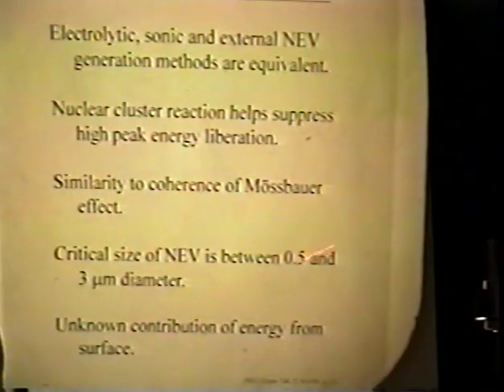At the critical size of the cluster for the kinds of energy densities we make must lie between about 0.5 micrometer and 3 micrometers in size. And we're getting a surface energy contribution from where we do not know. But there's something that produces this wildfire effect that, if it could be gathered up, would be a very useful form of energy to help create an energy gain device or more transmutation.